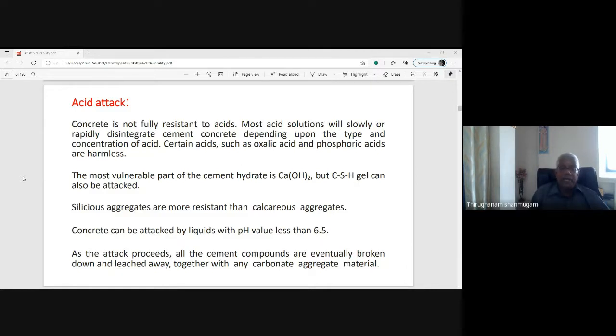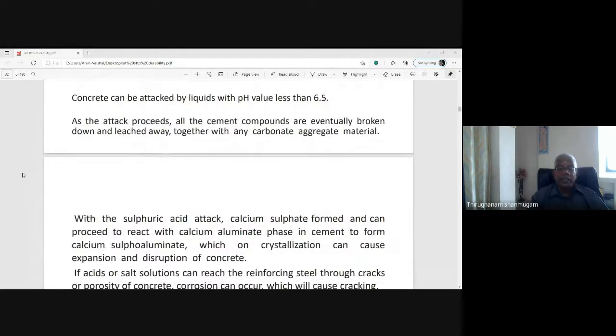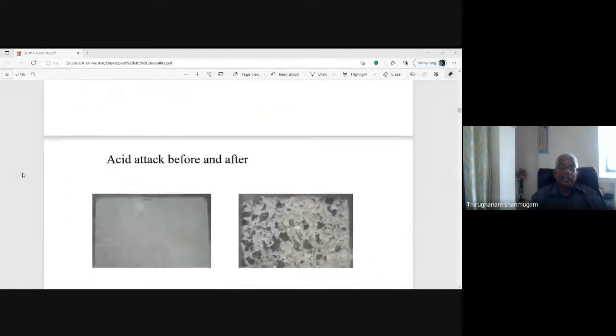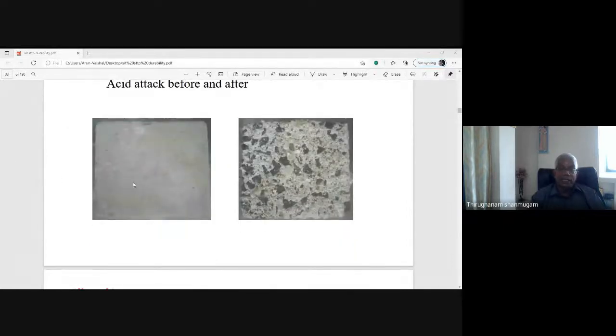Cement compounds are broken down and leached away. There is no cement content left in the concrete. This may be seen in this video. This is the surface of the concrete. If the concrete is attacked by sulfuric acid or any other strong acid, the cement paste is completely leached away, exposing the fine aggregate and the coarse aggregate. This concrete is completely deteriorated and it will not give durability.